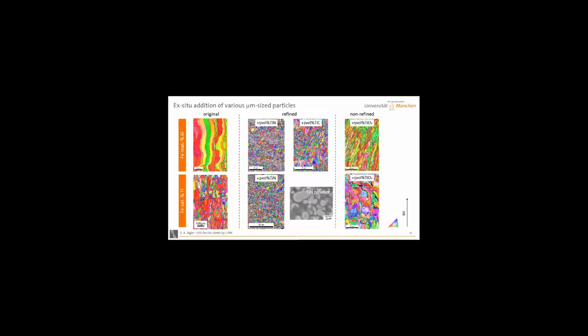And that is understandable because the phase predicted at 2% titanium is Ti2O3, or perhaps the particles remain TiO2. I don't know, to be honest. But in any case, you do not get grain refinement. In this case, here in the middle, with TiN and TiC, you do get grain refinement.